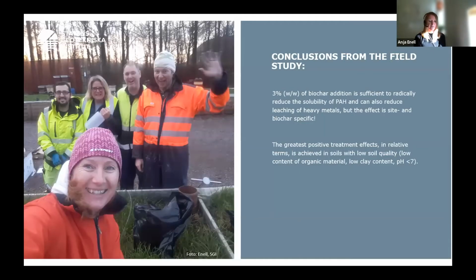So conclusions from the field study is that 3% of biochar is enough to see a drastically reduced solubility of PAHs and also a reduced leaching of heavy metals. But the effect is very site and biochar specific. So you will get the greatest positive treatment effects in relative terms in soil that has from the beginning a low soil quality. And by low soil quality, I mean low content of organic material, but also a low clay content and a pH less than 7.